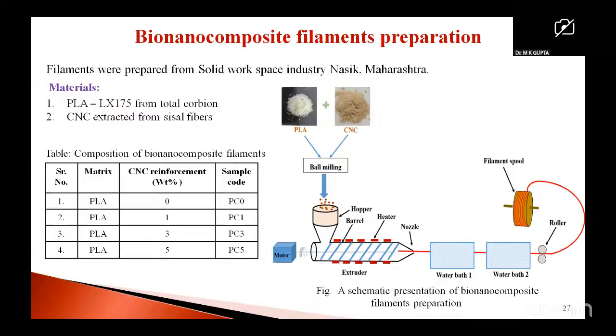First of all, PLA pellets and the CNC were both mixed in the ball milling. Then it was inserted into the extruder, and finally you can see the filament of this polymer reinforced CNC is prepared by the extrusion process. In this research, we have taken the concentration of the CNC as 1%, 3%, and 5%. As you see, the reinforcement capacity you can use for the cellulose is 1 to 5%.